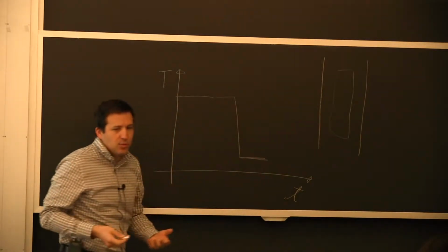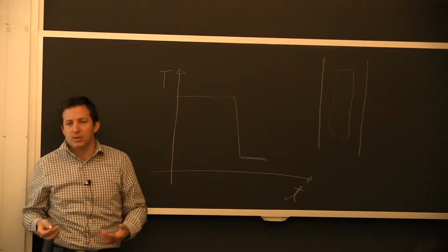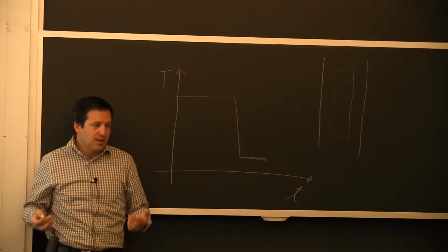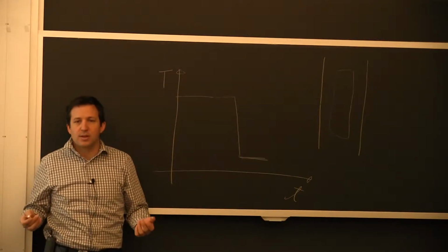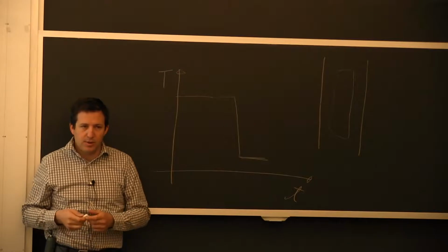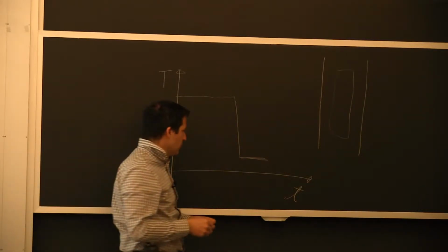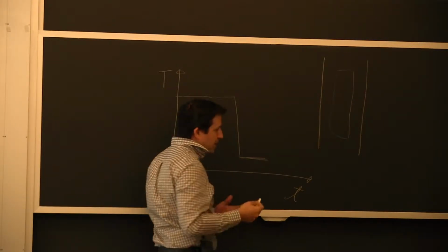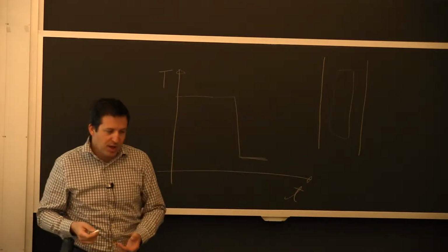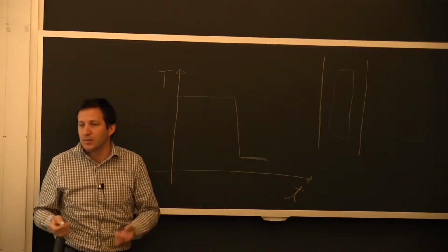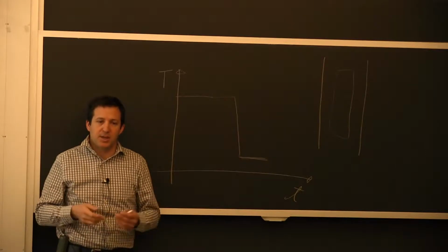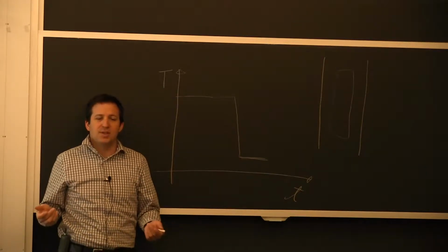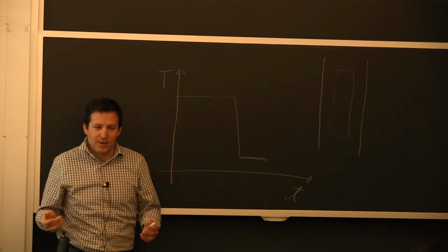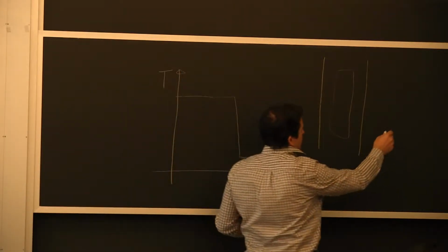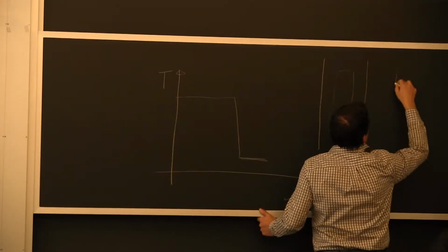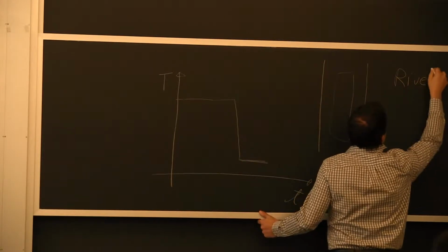because you quench, you didn't have the time to form the precipitates. What do the precipitates do? They increase your yield strength. They are obstacles to dislocations in aluminum. So what you do, depending on the alloy, I mentioned briefly about rivets, if you remember, rivets for aerospace. What I was saying, it's essentially a 2000 series aluminum alloy. If you remember from yesterday, the tempers, there's a temper, so I'm going to put it here, rivets.